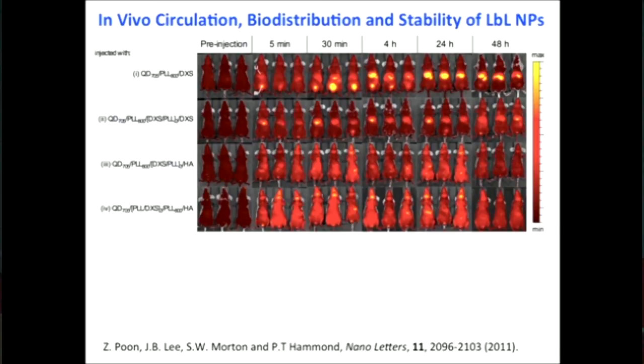We found that if we introduce just one more layer, when we go from 1 to 3, we actually get a much more stable system. And when you tail vein inject, it doesn't show up in the bladder or the feces anymore. It does accumulate more in the liver than we would like, and this is the liver region. However, if we use a different outer layer, dextran sulfate is a sugar, it's a common sugar, but we think it actually is binding to some receptors that are expressed in the liver in what are called Kupffer cells.